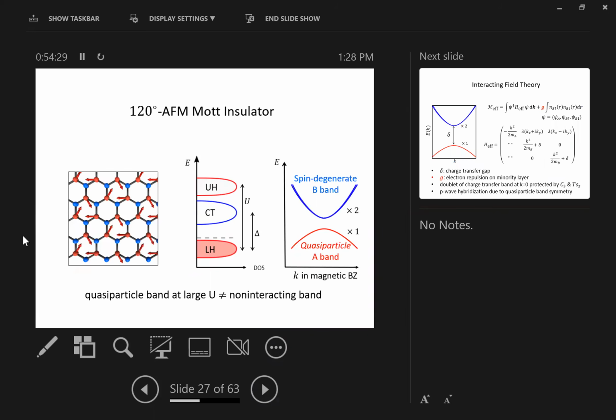Okay, so to just go through this, the state we start with is a Mott insulator on the triangle lattice of 1 layer. It has this 120-degree magnetic order. It is the canonical ordered state on the triangle lattice. Spins are in the XY plane and form this kind of a spiral order. And if we look at the quasi-particle, the holes, if I have holes moving in this Mott insulator state, it has its own band structure, which is what I mean by quasi-particle band structure. It's a band structure of the lower Hubbard band.